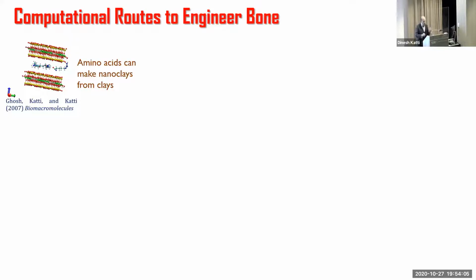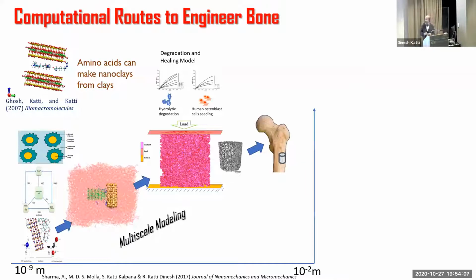And so we took those nanoclays and put them in our polymers and made scaffolds out of those. And as expected, our simulations also told us that the mechanical properties of our scaffold jumped up by 5-fold. And that was perfect, and that's exactly what we wanted. But then we saw something even more interesting happen.